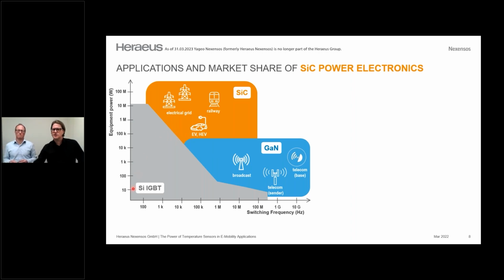There you can easily check that if you raise the power, that means you look here on the watt, silicon carbide is more and more interesting. That means the higher the voltage you want to transform, the higher the power you want to deal with, the higher the temperature is in the end. And with a typical IGBT silicon solution, it's not possible to work with temperatures over 170 degrees, which is easily possible with silicon carbide.